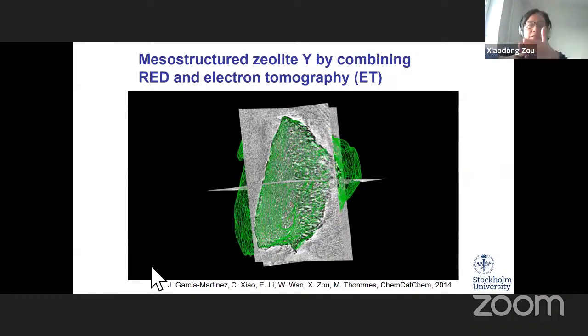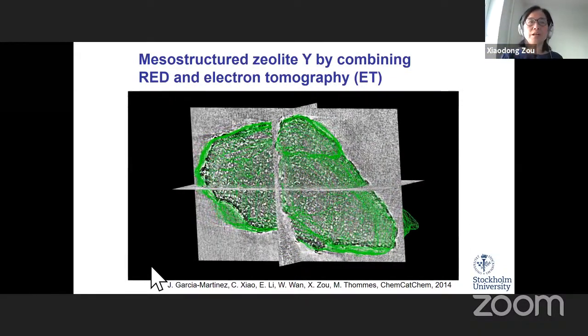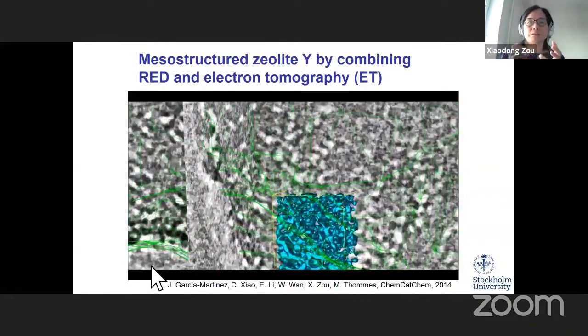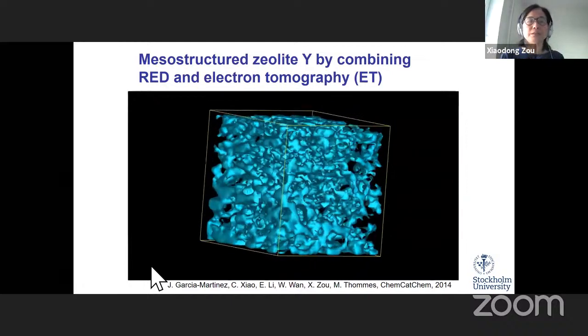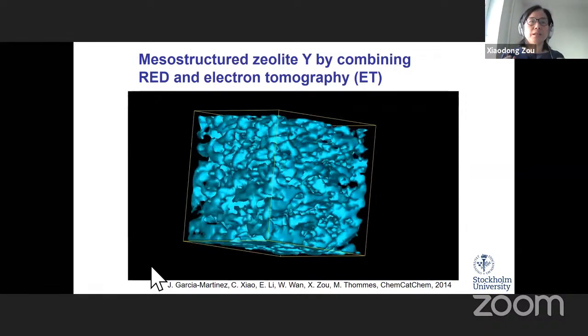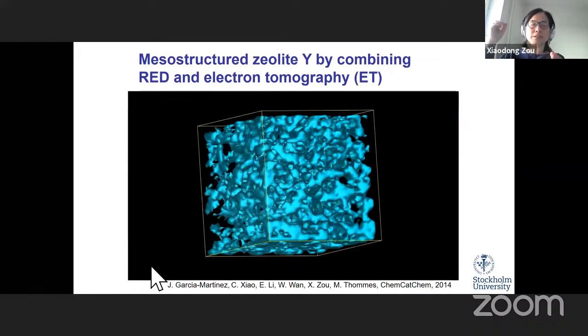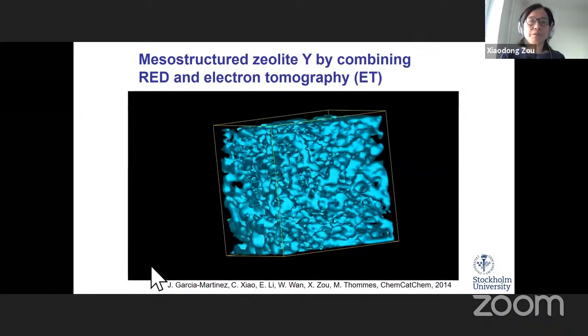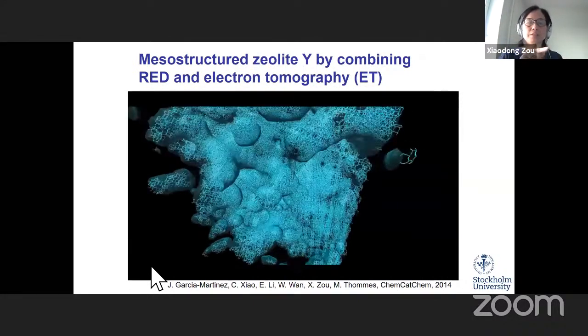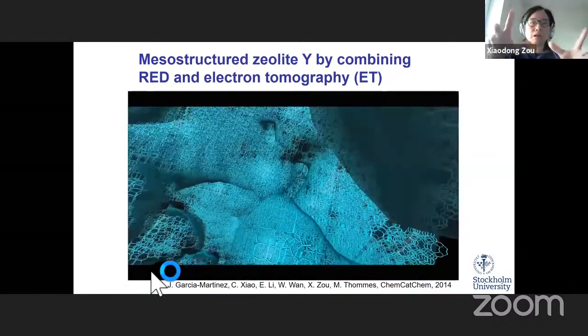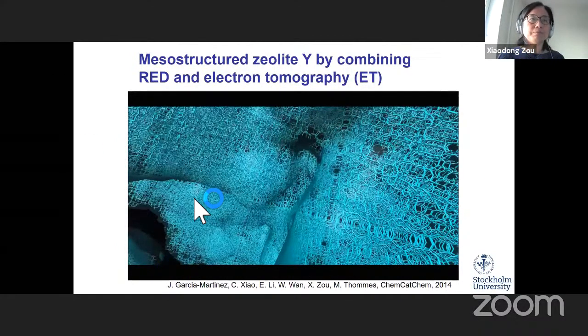And this is the 3D perpendicular cutting slices. As you see here, the white spots are the mesopores, but if you go a little bit closer to these mesopores, you see that they are very empty inside, which means that a molecule from one side can really go through this zeolite particle and get to the catalytic site and finally react, and finally the product will diffuse outside to the other side and exit the particle. So using this technique, we were able to find out the connectivity of the pores.